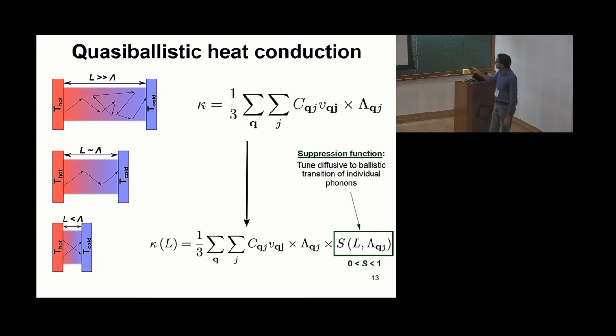You can show that in the diffusion regime, this comes from the Boltzmann equation. But if you have very little scattering, the expression morphs into a form that is usually a kinetic theory expression, with CV, V, and lambda. You can see that if all S's are 1, you get this expression.